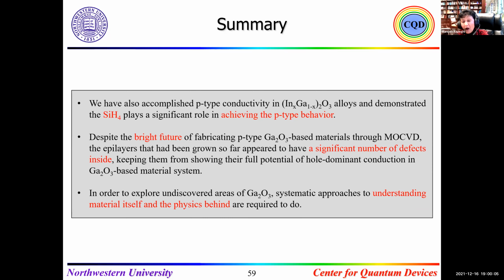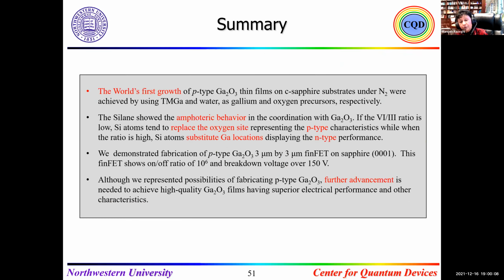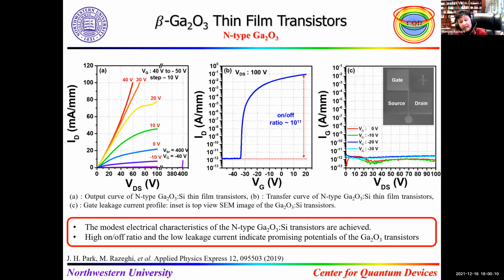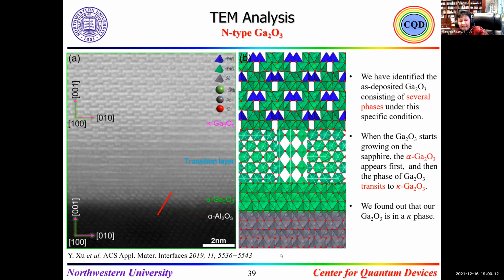But as you saw already, I showed you here, it's very hard to answer. Yes, here, they did exactly as you can see here, the interface, because you have to be very careful with the result of the TEM. They say that the best experts of the TEM say that if you give the same material to 10 different experts in different groups, you never can have two results exactly the same.